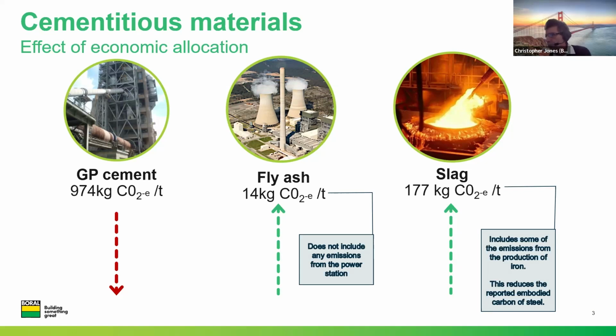Slag, however, is different. The steel manufacturers do make some money out of slag, and therefore some of the emissions from the production of the iron is attributed to the slag. This has the result of increasing the reported embodied carbon of the slag and lowering the reported embodied carbon of the steel. So we need to take this into account when comparing fly ash and slag.